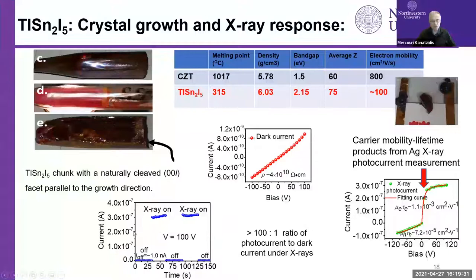So it looks like a very rapid response with a very high on-off ratio, a very low dark current with resistivity of about 10 to the 10th ohm centimeters. The IV curve in the presence of X-rays. And so in this direction, we're detecting electrons, and in the backward direction, we're detecting holes. And we can calculate the mu tau for electrons from this data, which comes out to about 10 to the minus 3, which is very good. And the holes, on the other hand, are very poor, maybe close to 10 to the minus 4. Nevertheless, this is a promising material that requires more work. The electron mobility that we measured in this material is about 100 square centimeters per volt second.